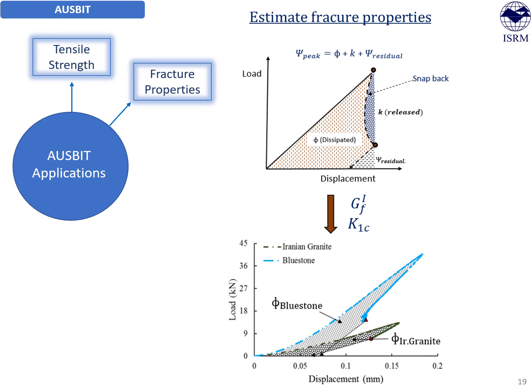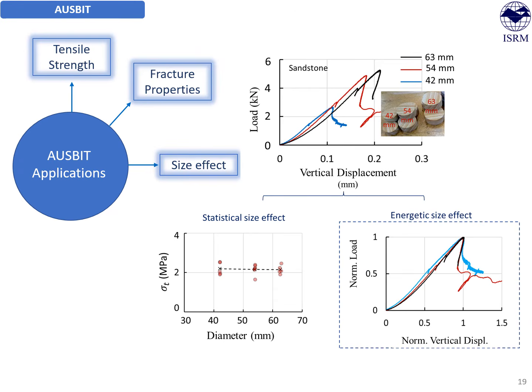With that, now we can calculate the fracture energy and fracture toughness using the same AUSBIT experimentation. In addition to this, we can also assess size effect. There are two types of size effect. One is statistical size effect and the second one is energetic size effect.